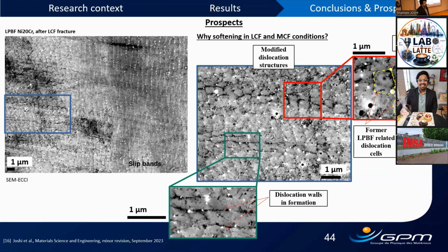So, well, I think the reason that nickel is also there is simply that nickel is 80% of the composition. So it has a statistical advantage over chromium. So this is also one of the reasons. And hence we focused more on chromium because, out of the 20%, we see the chromium-rich oxides first of all, and also chromium has a tendency towards forming oxides.